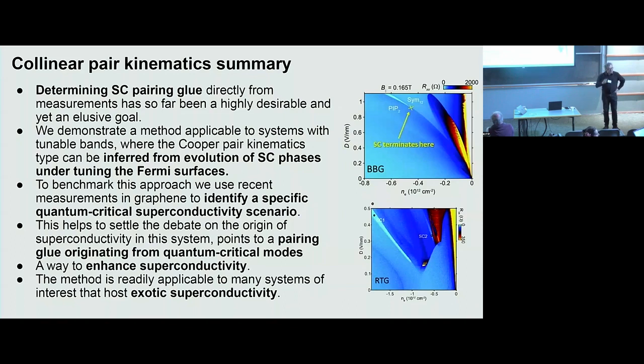So I want to first offer a falsifiable consequence. I think this mechanism would predict non-S-wave pairing within a valley, so some kind of P-wave, even within a valley. That means that now these systems are extremely clean. They're in the clean limit. That would predict that if you add a little bit of disorder, non-magnetic disorder with scattering within a valley, that should destroy superconductivity very, very rapidly. I don't call it falsified. Call it confirmed.